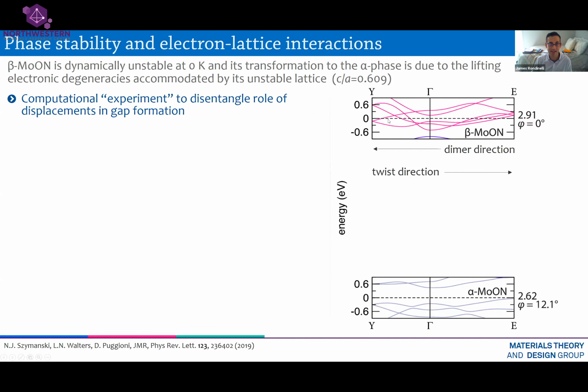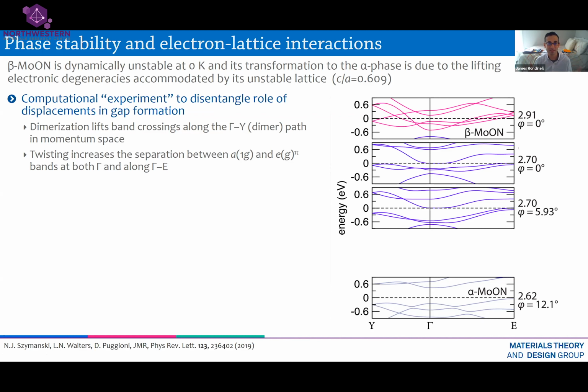And what we find is that the beta phase is a metal. You've already seen this in the density of states. And if I look from gamma to Y, I'm looking along the dimer direction in real space. If I look from gamma to E, I'm looking along the twist direction. So remember, these chains of moly atoms dimerize, but then they also twist a little bit. And both play an important role in the metal insulator transition. And with our first principles calculations, we can decouple them. This is something that's very difficult to do in the experiment because they occur simultaneously.